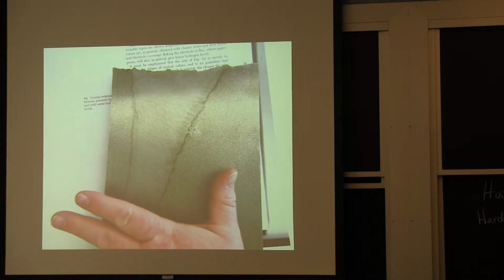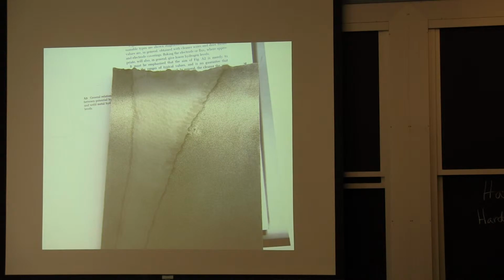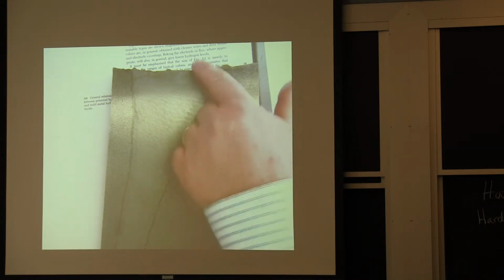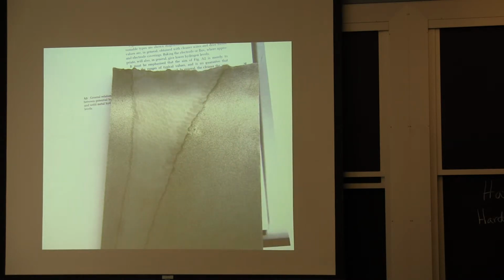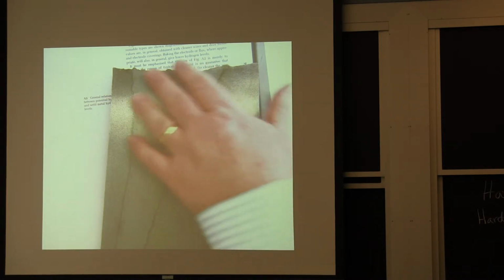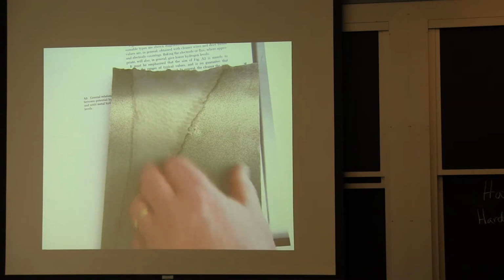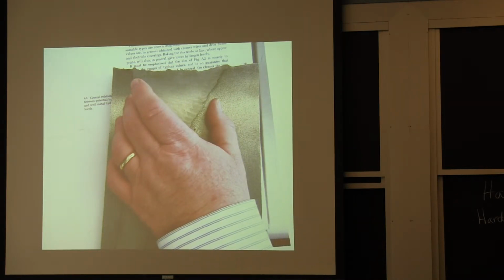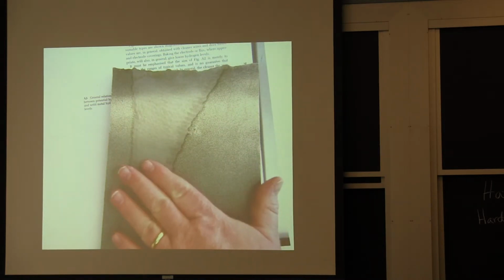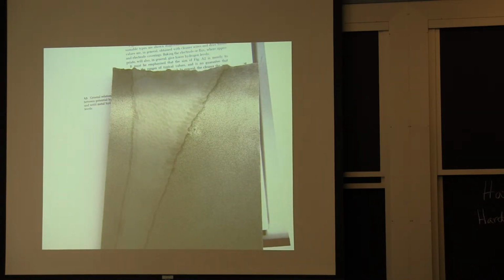This was about a 60-ton cap to the forging press. This is the top of the forging press. It was about 10 inches thick. The crack ran through a section that was about 14 inches in the direction that the crack ran. So they gouged it out. And the company that came in on an emergency basis to do the welding, this thing has about 300 or 400 weld passes. You can see each little pass of a stick electrode. You can see the heat affected zone is fairly narrow. We took a section here that didn't show, well, there obviously was no crack here.